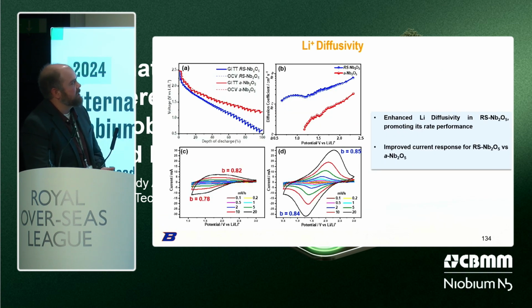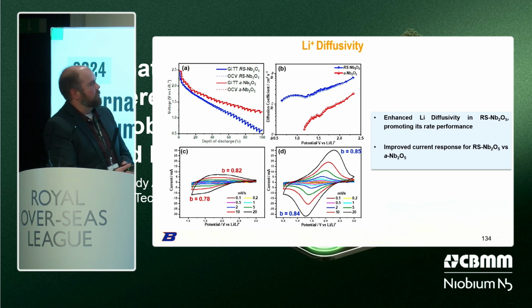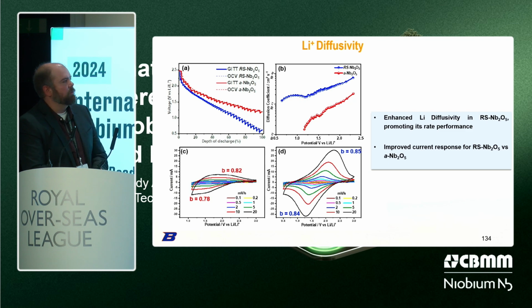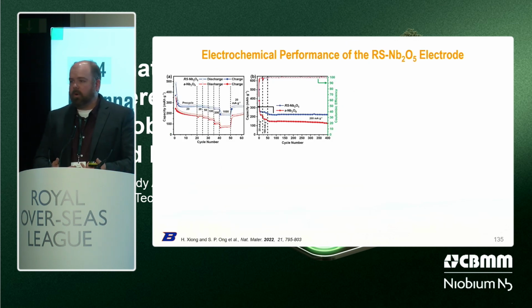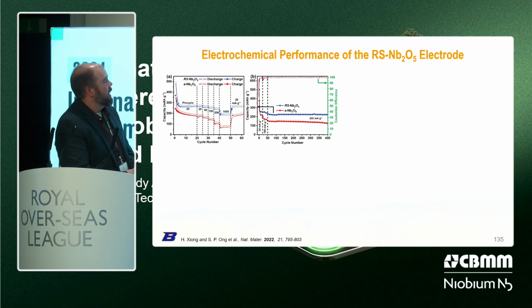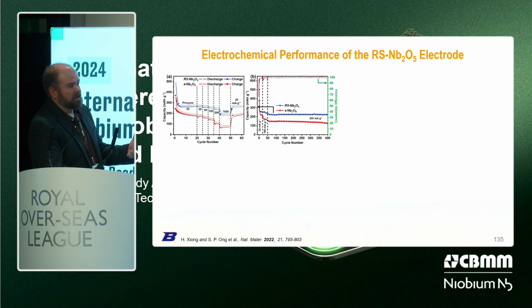So we have this rise in the lithium diffusivity, which was also demonstrated by GITT. And so in GITT, we're seeing that we have a faster rate of diffusion associated here, almost an order of magnitude larger. And then you have an improved current response between the rock salt and the amorphous, especially when it comes to the low voltages associated with them. Now, how do they perform as a battery? That is a really important part. Now, with that high electrical conductivity, which we talked about as being poor for niobium oxides before, if we improve that and we improve lithium diffusivity, this should help the rate capabilities of the materials.